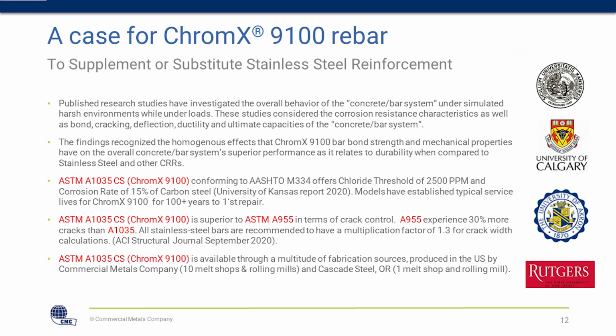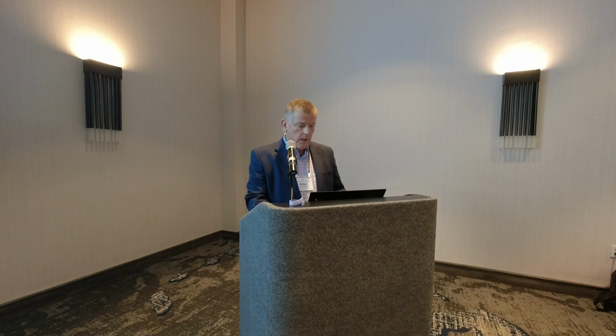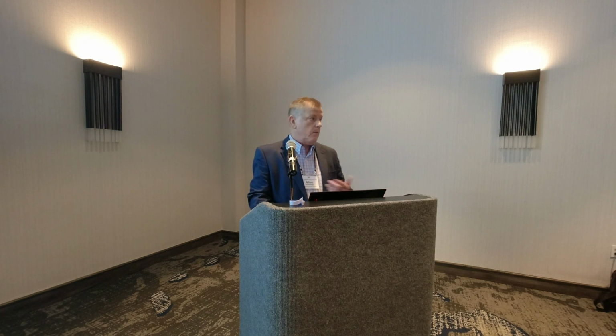And the ChromX, or the 1035 CS product, was developed specifically to passivate in concrete and to be used as dowels in pavements. And one of the things too is the raw materials are a little volatile with stainless, and they also are with ChromX. But the contribution that it makes is it's about 35 to 50% reduced cost over the stainless steel product.